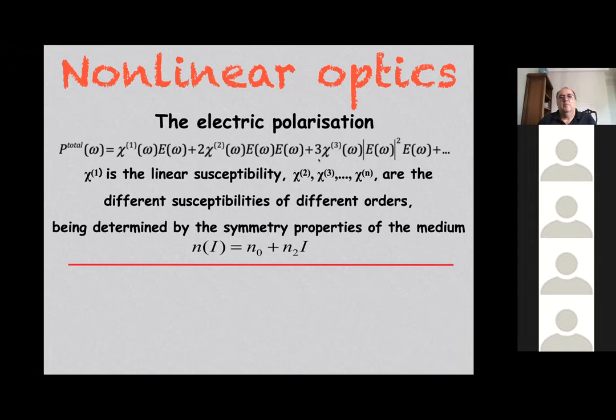So if you have a medium which is basically isotropic, with a mirror symmetry, chi 2 is expected to be zero, and chi 3 is the first nonlinear optical term that contributes to the total polarization. And we can analyze these different symmetry properties.